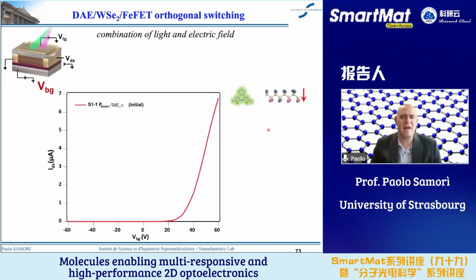Now we try in this slide to combine the two, which is the most important slide of this story. We start with the higher current, where we have the ferroelectric system in the P down state and the diarylethene in the open state. And then in this case, we have irradiated with UV light, and we bring the diarylethene to the closed state. And so we create some traps for the charges, and we decrease the current through the junction. Note that the ferroelectric is still in the P down state. Then at this point, the polarization direction of the polymer was switched from downward to upward by applying a negative top gate bias of minus 60 volt.